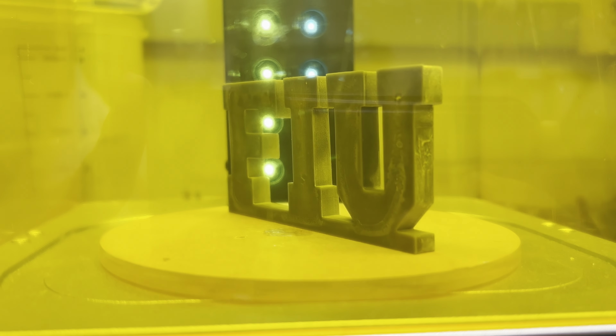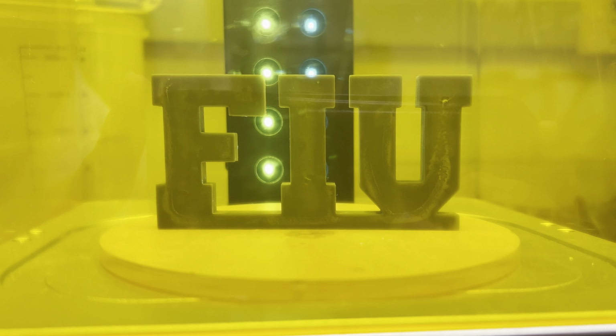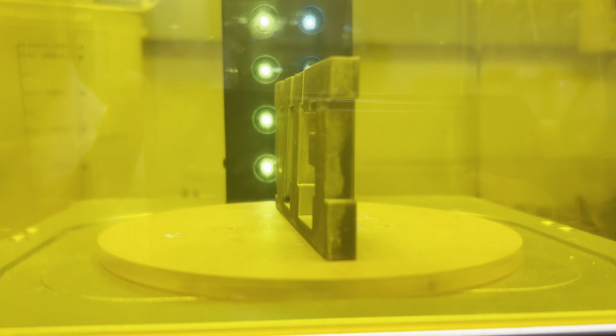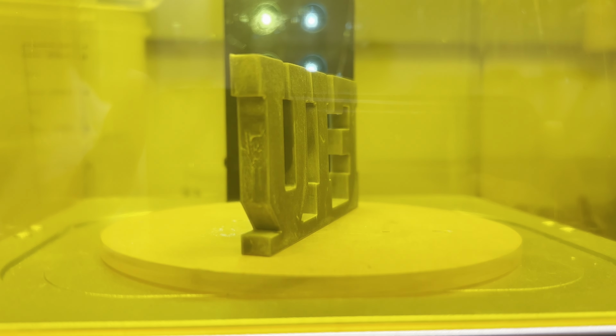After the print is scraped off the print bed, it is cleaned with IPA and the part is placed in a chamber with a spinning table and UV light. It's placed in this chamber for the same amount of time that it took to print the part. This cures any resin that remains in the crevices of the part.